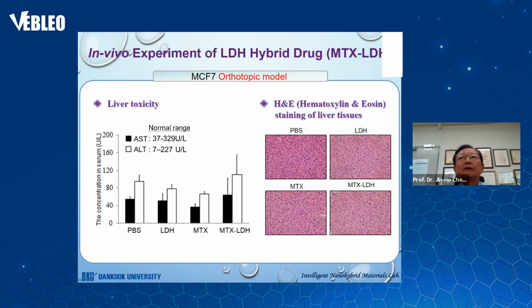And as you can see in this slide, AST and ALT levels of LDH MTX injected mice were found to be in the normal range. In addition, histopathological analysis of hematoxylin eosin stained liver sections, as you can see on the right-hand side, does not show any morphological abnormalities related to liver injuries in any of the treatment groups. It is therefore concluded that the LDH MTX nanoparticle drug does not induce any liver toxicity and inflammatory immune response after systemic delivery.